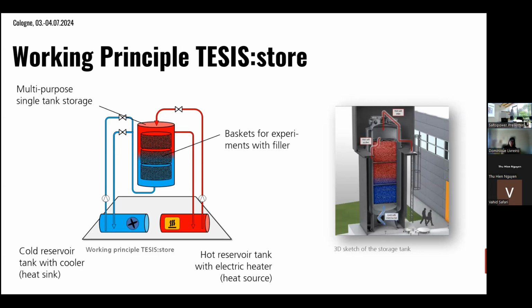So basically the inflow is from the top and the outflow on the hot side is here from the side, whereas on the cold end we enter and exit the tank both from the bottom. There's some kind of siphon here. The reason for that was that the cold tank is made of a different material, so in case of any failure, we can make sure that there's no uncontrolled inflow of salt into the cold tank.